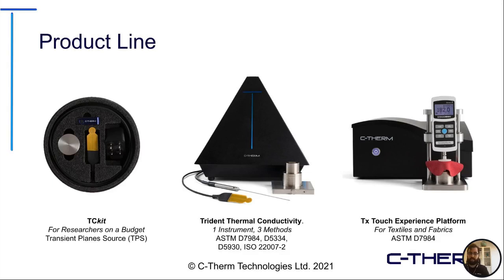On the far right, you'll see our TX Touch Experience platform, which is a dedicated unit for testing textiles and fabrics according to the ASTM standard. And what you see here is the compression test device that allows you to properly change and understand the effects of compression on the material you're testing for effusivity and conductivity. So if you're looking for a broad research platform for things outside of just textiles and fabrics, Trident can be a platform that you look at. If your main focus is textiles and fabrics and focusing on the ASTM standard, TX is where we would lead you.